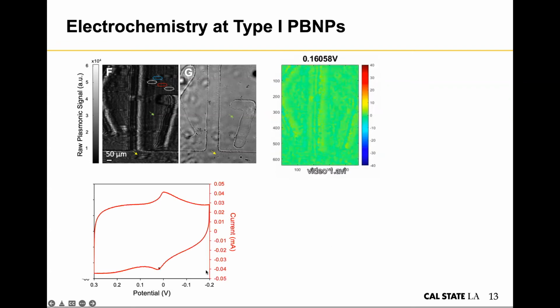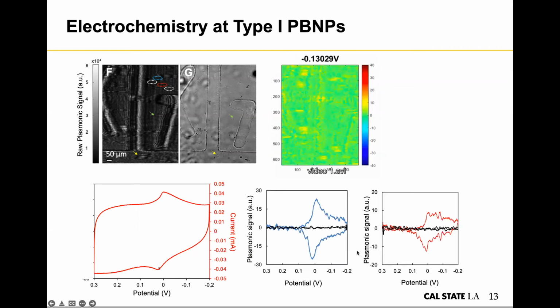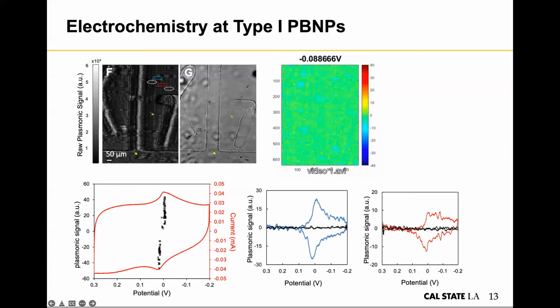And here is the potentiostat CV we obtained from the electrochemical setup. And here are two examples of Prussian blue nanoparticles. There's one here, and its surrounding background area. So you can see that we got a very nice symmetric peak, which corresponds to the thin layer electrochemistry of Prussian blue coated on the electrode surface. And if we overlay the peak potentials of those Prussian blue nanoparticles with the potentiostat CV, we can see that the peak